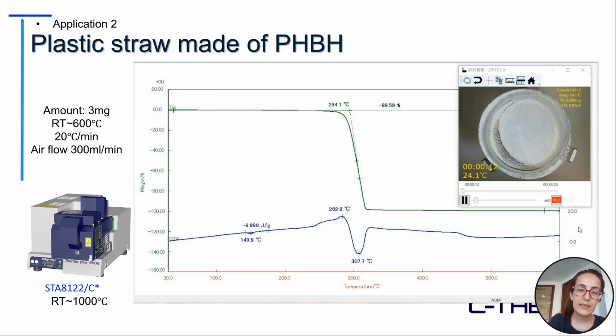In these thermograms, we observed the changes in the properties of the samples visually. At the end of this webinar, I will show you how the sample changes when we heat it from room temperature to 600 degrees Celsius. Without this observation, we couldn't tell whether this small exothermic peak at 149 is related to melting or another transition, and the big endothermic peak at 306 is related to the decomposition of the PHBH.